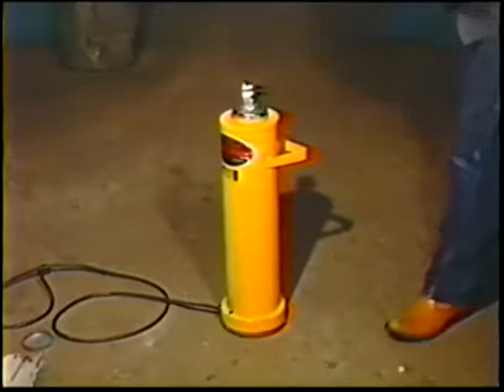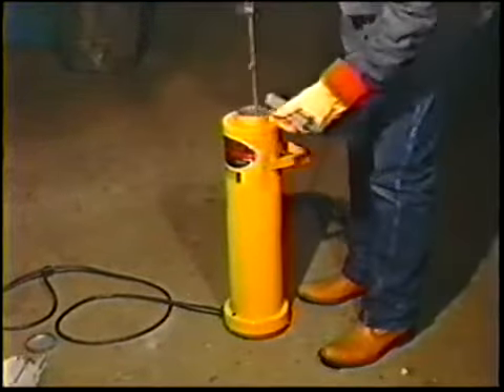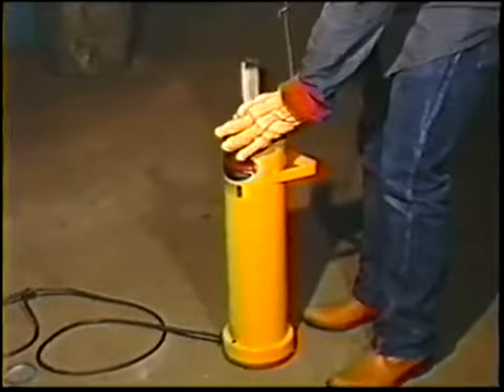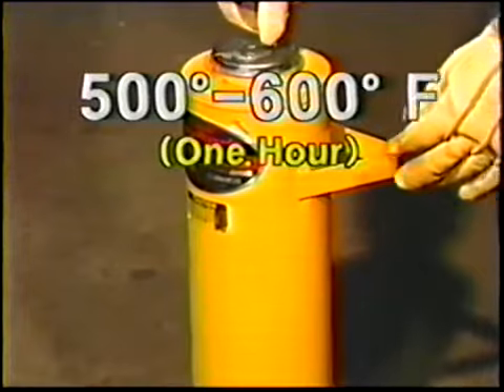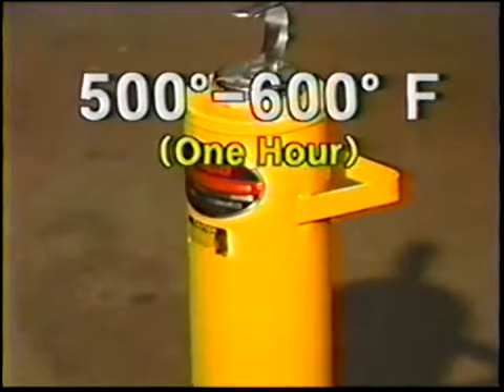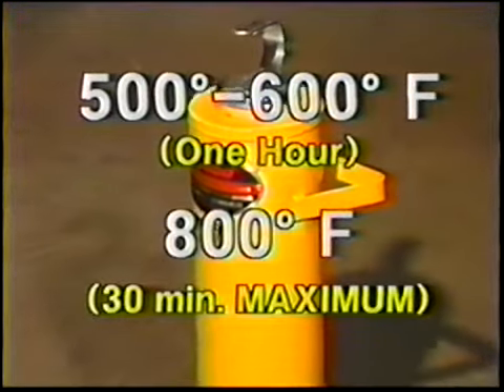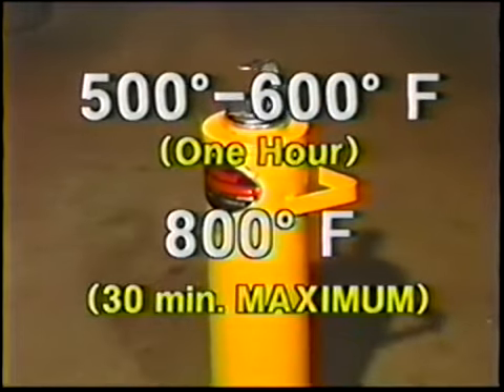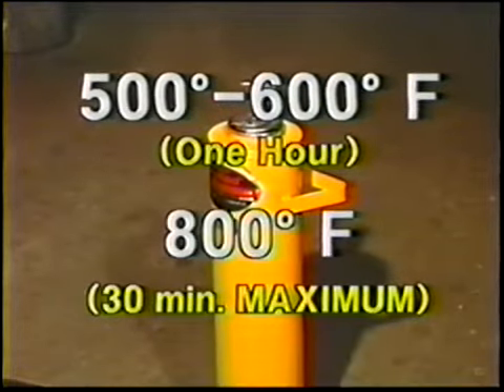Electrodes that have been exposed to moisture can be reconditioned by heating in an oven for about an hour at 500 to 600 degrees Fahrenheit. The maximum temperature is 800 degrees for no more than 30 minutes. Electrodes should not be reconditioned more than 3 times. Reconditioning weakens the binder that holds the flux coating to the wire, and the coating will chip or flake off.